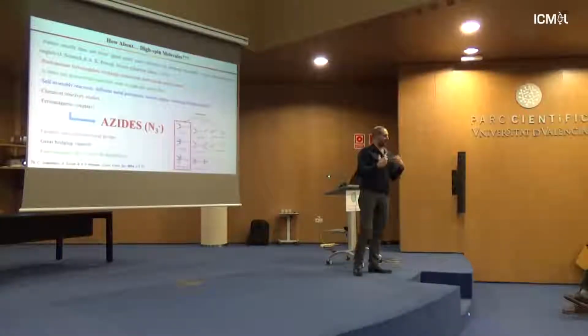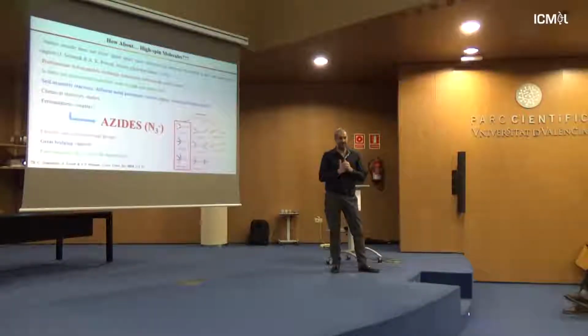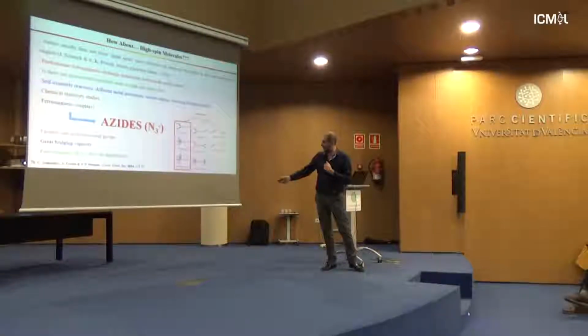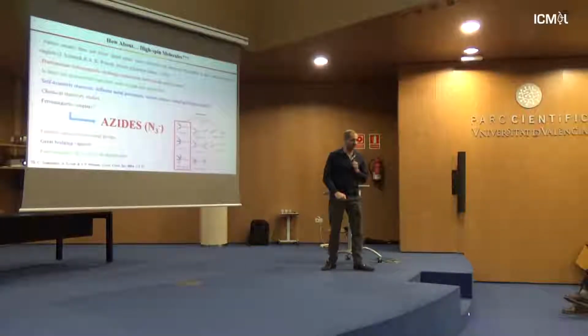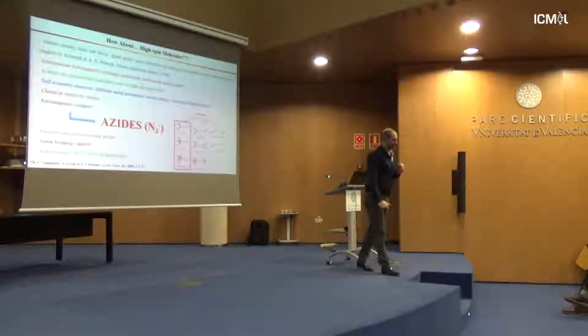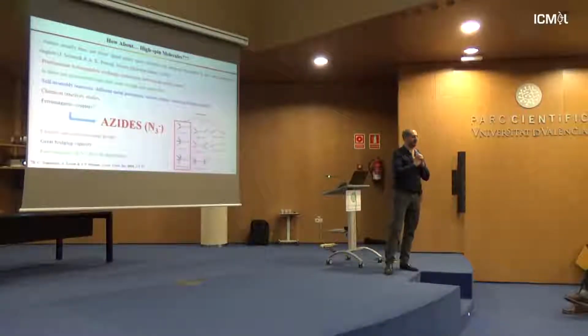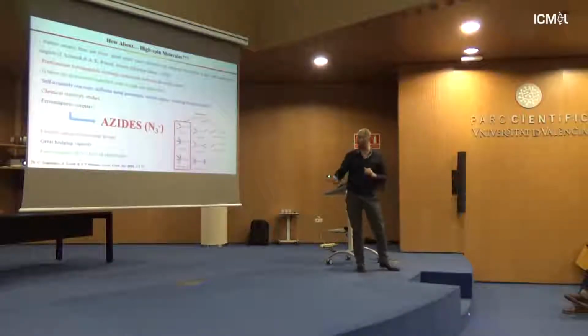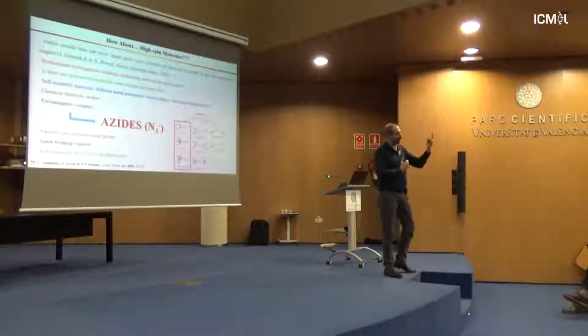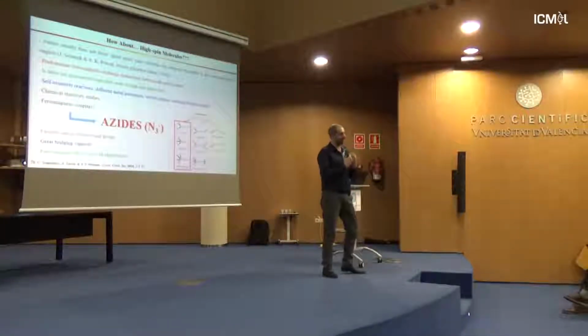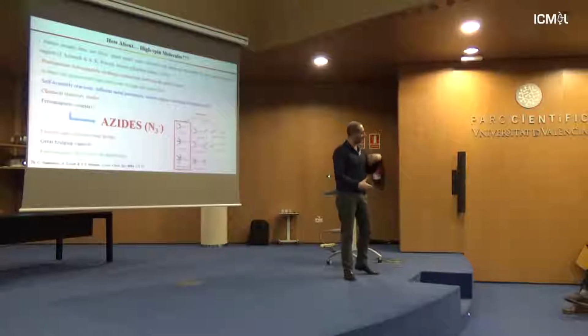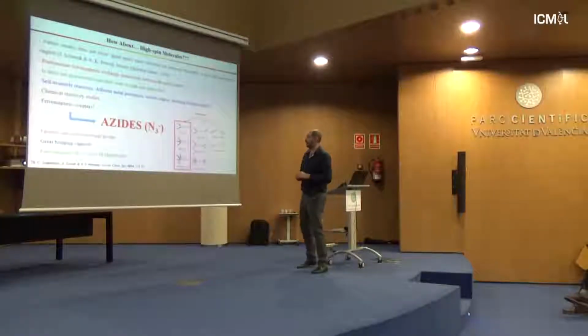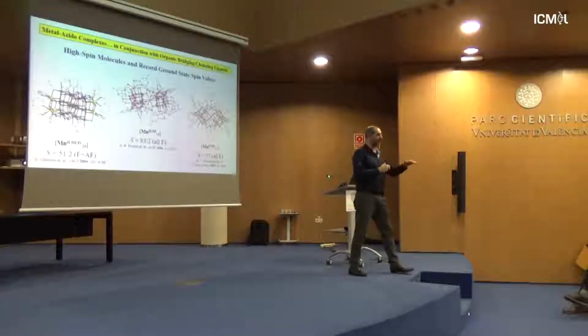And these ligands are azides. They are not uncommon to you, especially in the Spanish community, okay? They are not uncommon, and we all know that azides in that end-on ligation mode, bridging 2, 3, or 4 metal centers, only under that, is a guaranteed bridging mode to promote ferromagnetic exchange interactions between the metal centers. That's good, that's great. We have ferromagnetic couplers, but azides are the only ferromagnetic couplers. The question is how you are going to make a high nuclearity compound where, literally speaking, you need to have not only azides so far, you need to have all of these other components, organic ligands, maybe some oxido, hydroxido, and so on. It's really difficult.